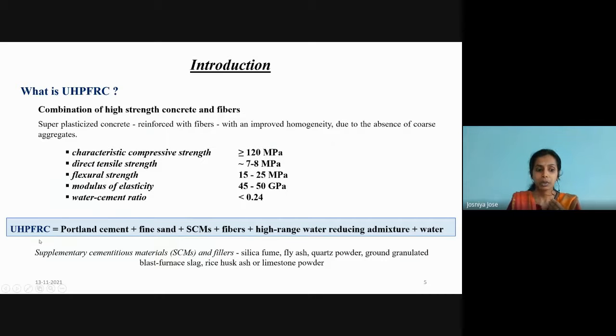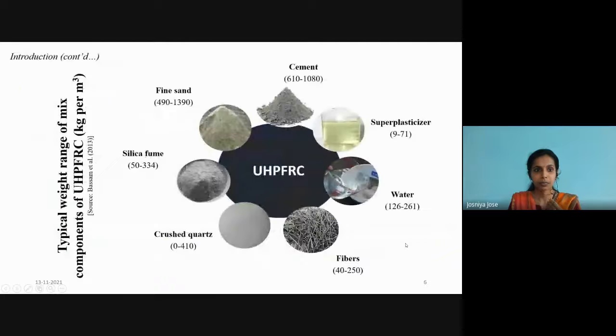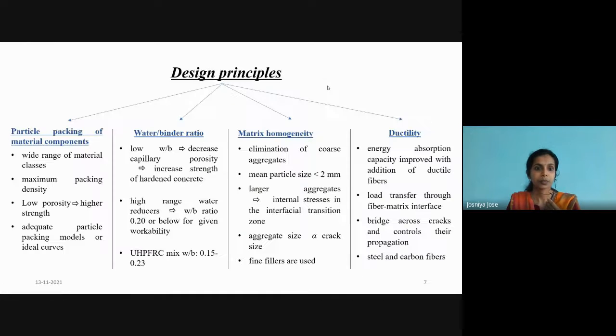The matrix of UHP FRC consists of Portland cement, fine sand, supplementary cementitious materials, ductile fibers, and high-range water-reducing admixtures, specifically polycarboxylate ether-based superplasticizers, along with small amounts of water. So this is the weight range of the mixed components of UHP FRC. As we said, it consists of higher cement content, up to 1080 kg per meter cube.